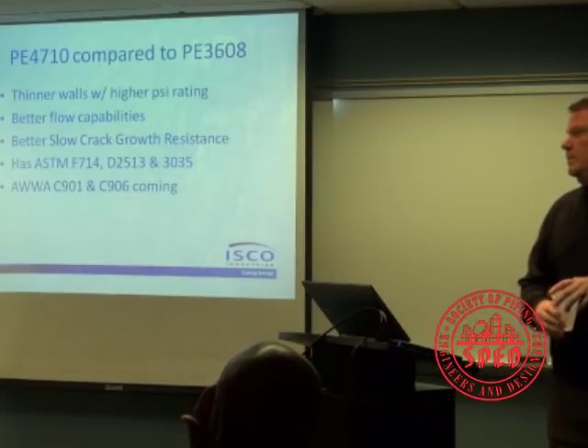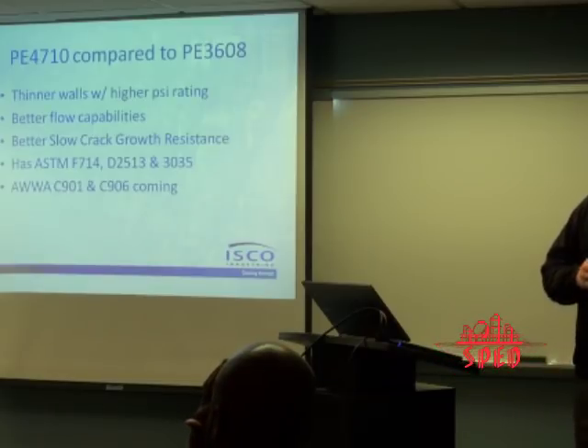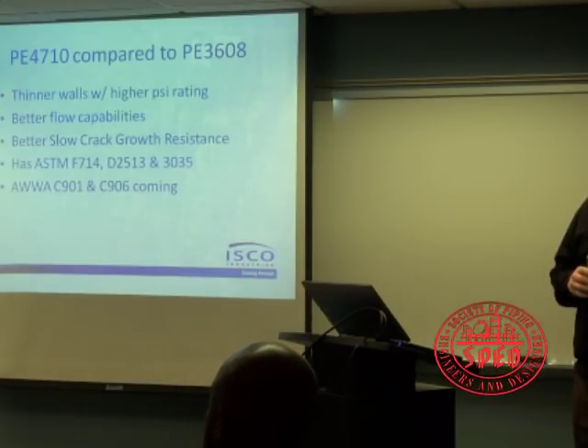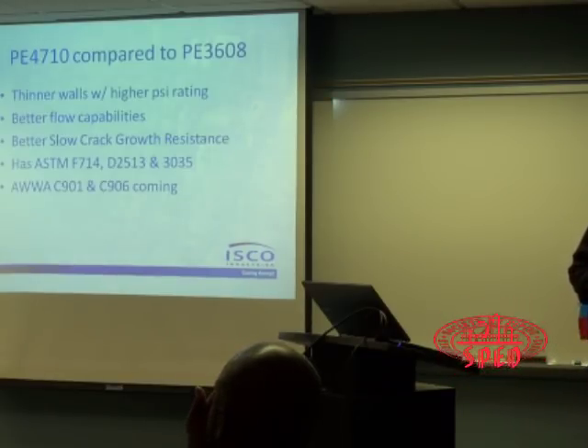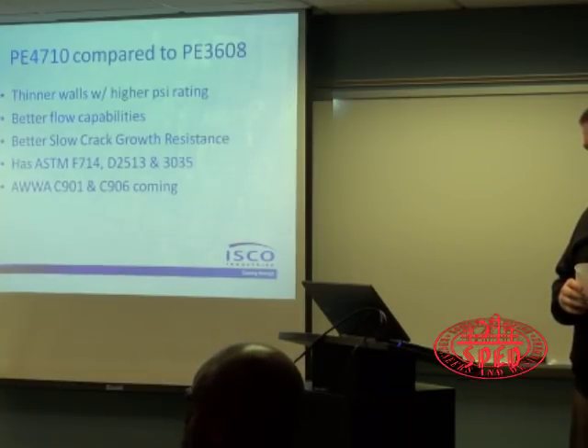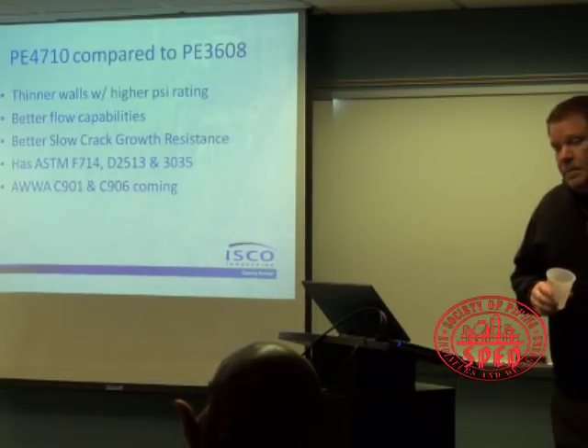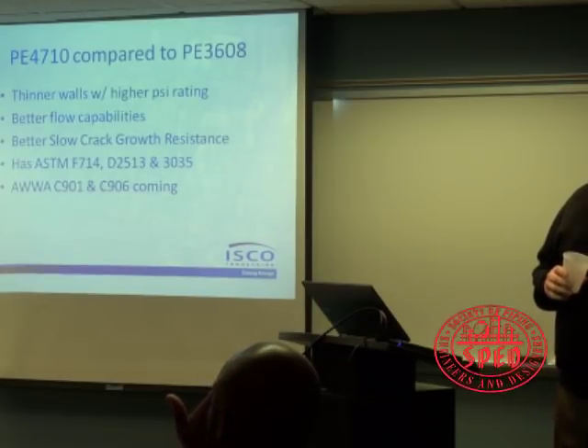There's a couple of surprises in HDPE pipe. One is a good surprise: it's got about a 400% yield before failure, which is really good. Correct me if I'm wrong. Another surprise is that it has a big coefficient of expansion. This Catawba plant that used it for water feed lines from one of their pond heat sinks had to do a lot of anchoring where it entered the power station because the coefficient of expansion was so great. They had to pay a lot of attention to anchors and wall penetrations.